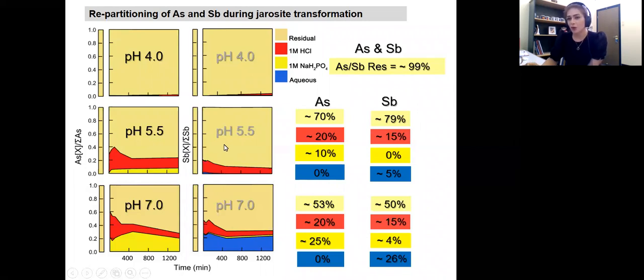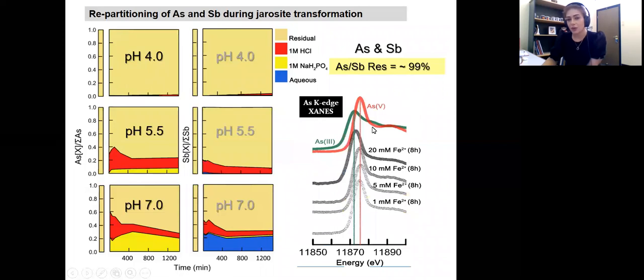But it's important to know if this arsenic is arsenic 3, the trivalent, or the pentavalent arsenic. Because as I mentioned, the pentavalent forms of arsenic and antimony are less toxic than the trivalent. So we analyzed our samples for speciation, and we took our samples to the synchrotron to see if this arsenic is arsenic 3 or arsenic 5.